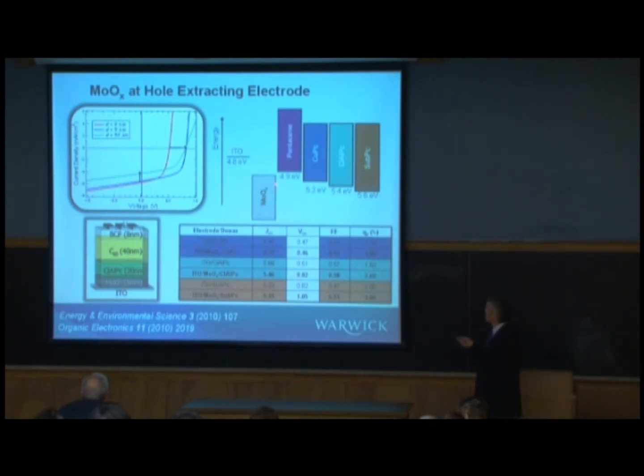Now, we looked at that in combination with a number of different donor materials to see whether you could improve all these devices just by inserting molybdenum oxide, and the answer is some yes, no, others. So if we take chloroaluminium phthalocyanine with or without molybdenum oxide, then you do improve the voltage quite significantly and therefore the efficiency. If we take our subphthalocyanine donor with and without the molybdenum oxide, again, you improve the performance from 0.8 to 1, and again, you improve the efficiency.